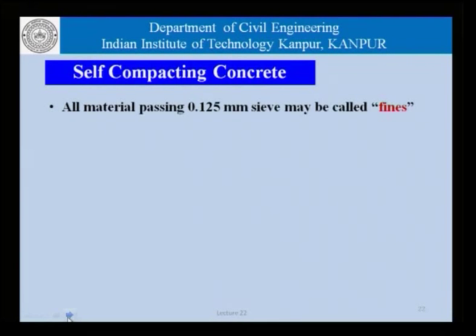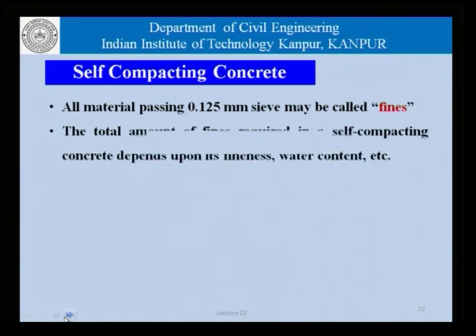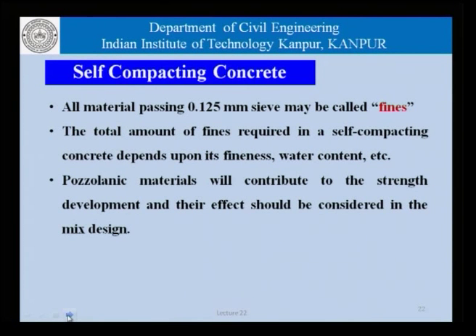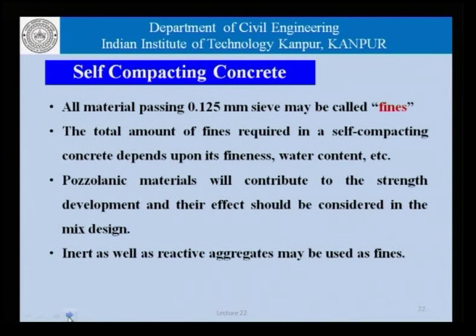Now, coming to self-compacting concrete, all material passing through 0.125 mm sieve may be called fines, and that is how we were trying to define the fines in the previous slide. The total amount of fines required in a self-compacting concrete depends upon its fineness, the water content, and so on. Pozzolanic materials will contribute to their strength, and their effect should also be considered in the mix design. Of course, we could use inert as well as reactive aggregate sometimes in fines, but with caution.